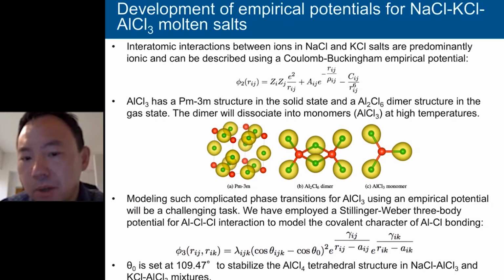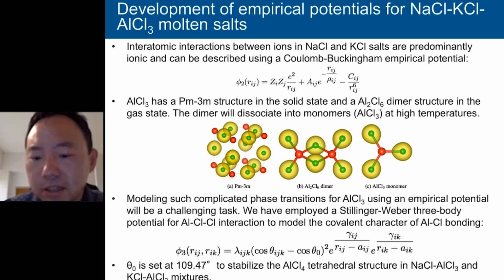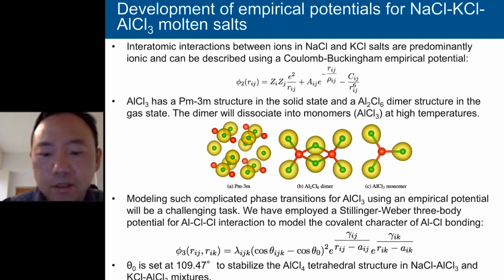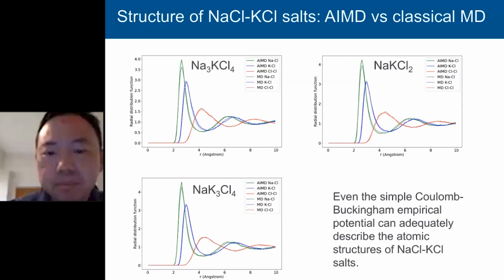structure, which has been experimentally observed in mixtures of sodium chloride and aluminum chloride, and also potassium chloride and aluminum chloride. Due to using a fixed angle theta, this model will not be able to predict the formation of these kinds of monomers anymore. So this will have some consequences, as I will discuss shortly.